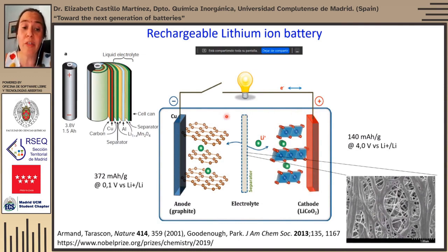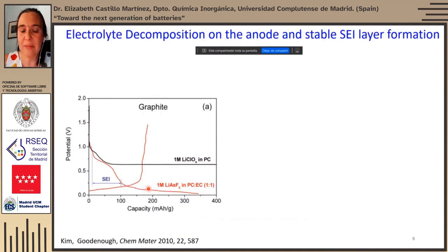As you can see, both the anode material and the cathode material have a layer structure, and they have capacities of about 370 milliamp hours per gram and 140 milliamp hours per gram. You don't need to remember these numbers, of course, but this is to give you an idea, as I will be talking to you about other values for other materials that have been developed. And what is important is that the voltage difference at which the redox reaction takes place on both the cathode and the anode is quite large, approximately 4 volts.